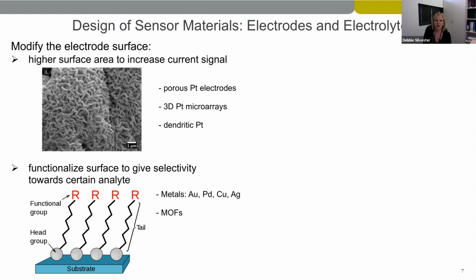And when we're looking at designing better sensor materials, there's a couple of things that we can do. So we can modify the electrode surface. So for example, we can use a platinum surface and change the surface area. My group and I have done some work on this. We've made porous platinum electrodes. We've also made 3-dimensional microarray electrodes and made dendritic structures. And these are all very useful to increase the surface area and improve our analyte response.